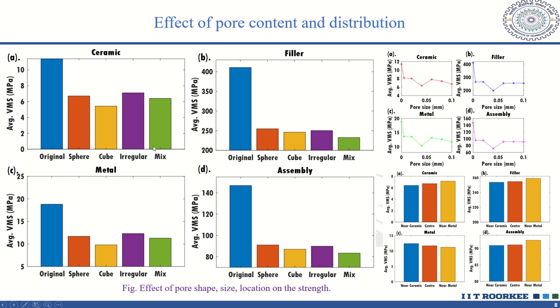And as we found, the joint assembly containing mixed shaped pores of 0.04 mm size and present near the ceramic material interface can be used.